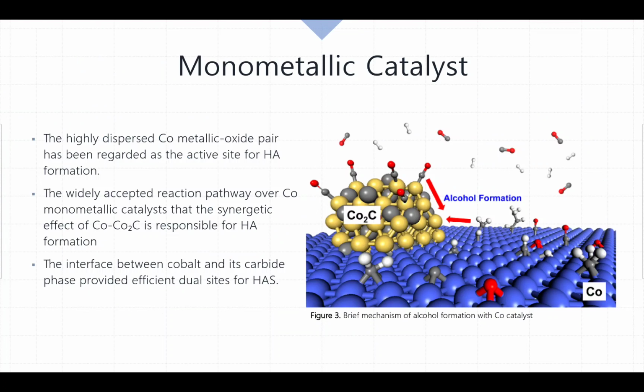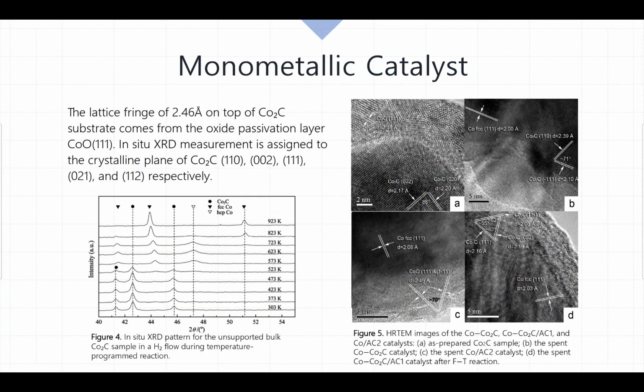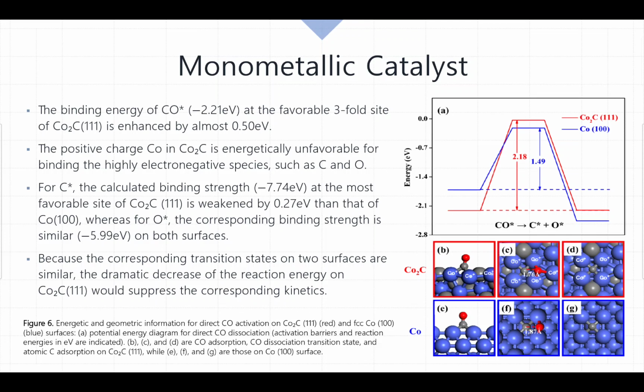The highly dispersed cobalt metallic oxide pair has been regarded as the active site for higher alcohol formation. The cobalt metal cobalt carbide catalyst was tested free of promoters and showed good performance for higher alcohol synthesis. The results were in agreement with the widely accepted reaction pathway over cobalt monometallic catalyst, that the synergistic effect of cobalt metal and cobalt carbide is responsible for higher alcohol formation, with metallic cobalt active for carbon monoxide dissociative adsorption and subsequent carbon chain growth, and cobalt carbide active for non-dissociative CO adsorption and subsequent CO insertion into the linear hydrocarbon intermediate. The interface between cobalt and its carbide phase provided efficient dual sites for higher alcohol synthesis.